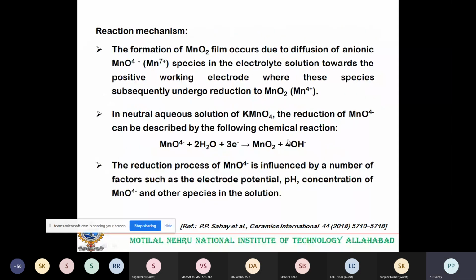What is the reaction mechanism? Here, we have used the precursor KMnO4, potassium permanganate. You will see there are a number of precursors available that can be used, like manganese sulfate, manganese acetate. Then I used the KMnO4, and later on you will see that even the electrochemical performance depends upon the precursor used to prepare the films. Here I have used the KMnO4.